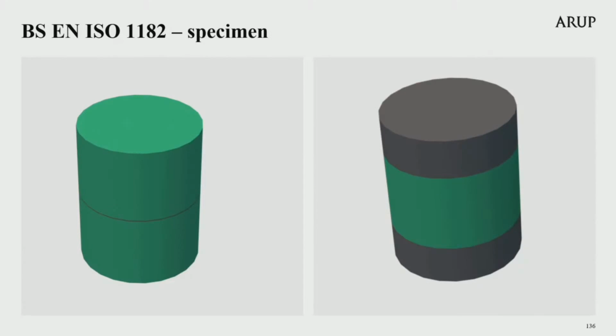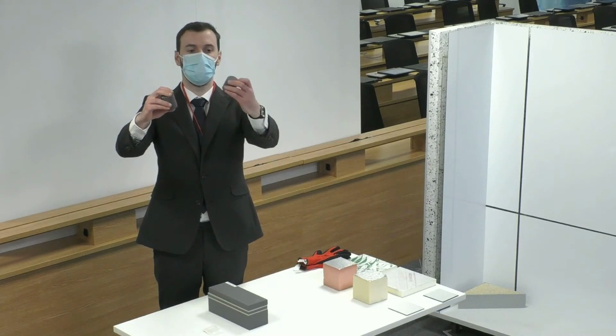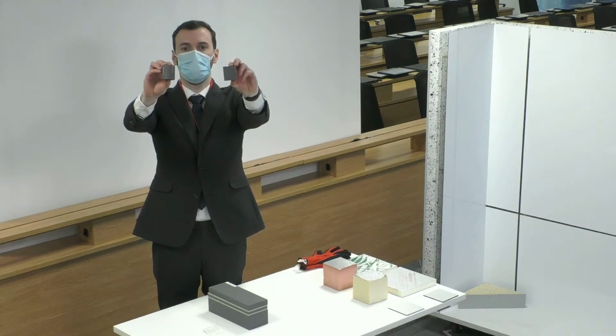5 cylindrical specimens are prepared, each with a diameter of 45 millimetres and a height of 50 millimetres. They are tested individually, but data is required from all 5 specimens to determine the final test result. If the thickness of the material is different to 50 mm, specimens may be layered and then secured with steel wires, or the material thickness may be adjusted. Tom is now holding up examples of these specimens for the European test.